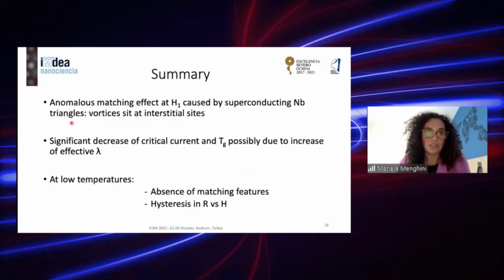So with all this, I just want to summarize our results. I think I clearly show that we observe an anomalous matching effect at the first matching field that is caused by these superconducting niobium triangles, and that's due to the fact that the vortices sit at these interstitial sites between the triangles. We observe also a significant decrease of the critical current and the critical temperature, possibly due to an increase of effective lambda in these hybrid structures. And finally, that at low temperatures, we observe an absence of matching features and an appearance of a hysteresis of the magnetoresistance.